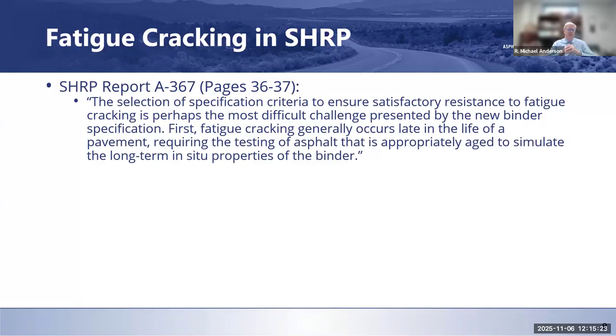And so they recognized during SHRP that it's perhaps the most difficult challenge and how to put it together. And they talk about it first occurring late in the life of a pavement. So what that means is you've got to test the asphalt material in a stage that simulates what happens after it's been in service for a number of years. That's really at least part of the reason why the pressure aging vessel was developed, to simulate that longer term aging that we were going to see in the binder, so that you could characterize what it's going to look like after it's been on the road several years.